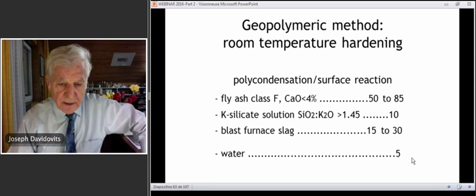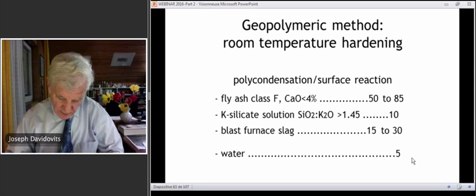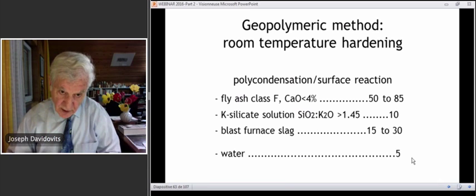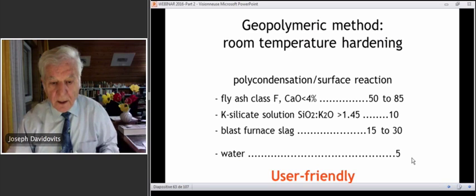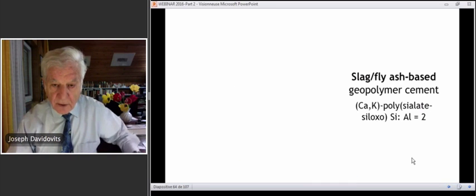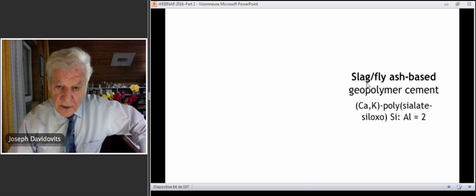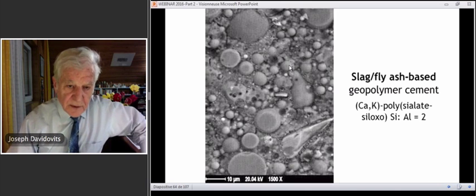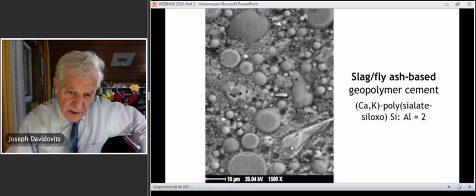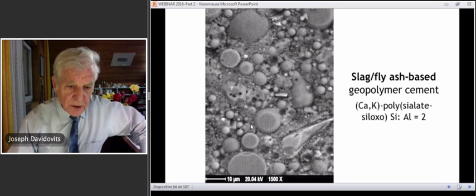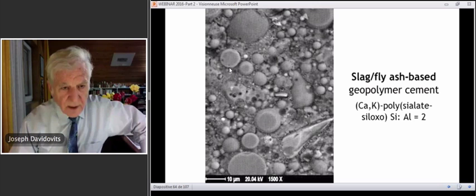This is geopolymer cement. Fly ash-based geopolymer cement, user-friendly, room temperature hardening. And if you look under the electron microscope, you have your slag fly ash-based geopolymer cement, the geopolymer matrix, that is a poly(sialate-siloxo), in between the spheres. So you have the spheres, they are intact. Here we have a remain of the blast furnace slag. And then in between we have our geopolymer matrix interacting with the surface of the fly ash.